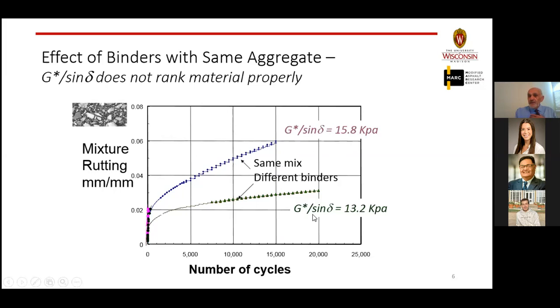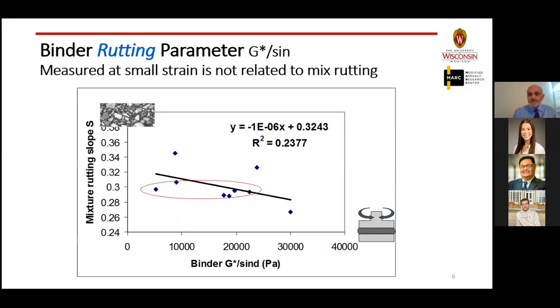So there is not only a theoretical dilemma with our use of the small strain, there is actual lab and field data showing mixtures behaving very differently when you go to higher stresses and strain. This is a set of data from this NCHRP report. It's actually a published chart in that report, which compares mixture rutting, looking at the creep rate, or the slope here called S, which is the secondary slope rate, versus the binder G star sine delta.